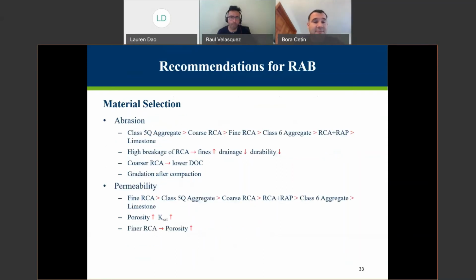Next slide, please, Raul. And again, abrasion, RCAs seem to have a higher abrasion, so it's recommended that gradation after compaction needs to be looked at. And for coarser RCA, maybe use a little bit lower degree of compaction. And permeability-wise, overall, at the moment, the field and the laboratory permeability test results show that hydraulic conductivity of RCA seems to be higher than limestone. But of course, long-term performance needs to be checked in future studies. Next slide.